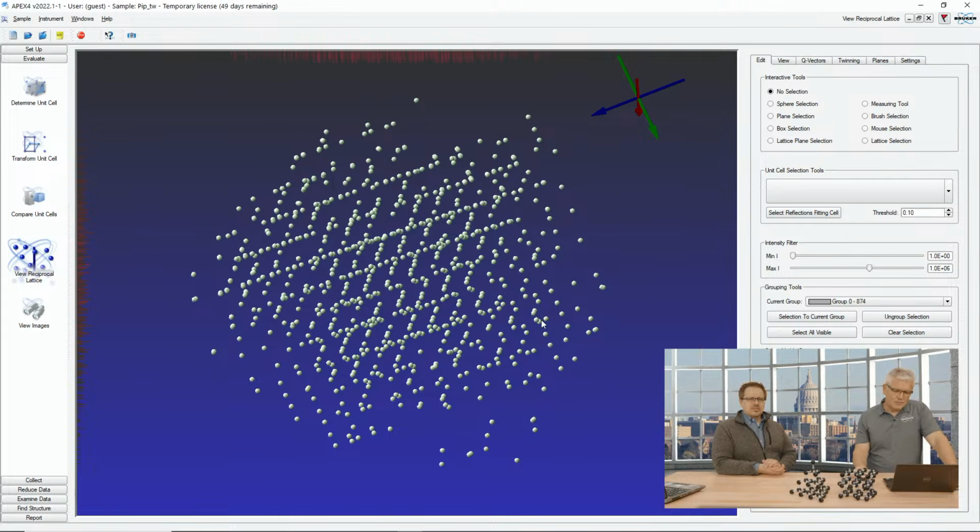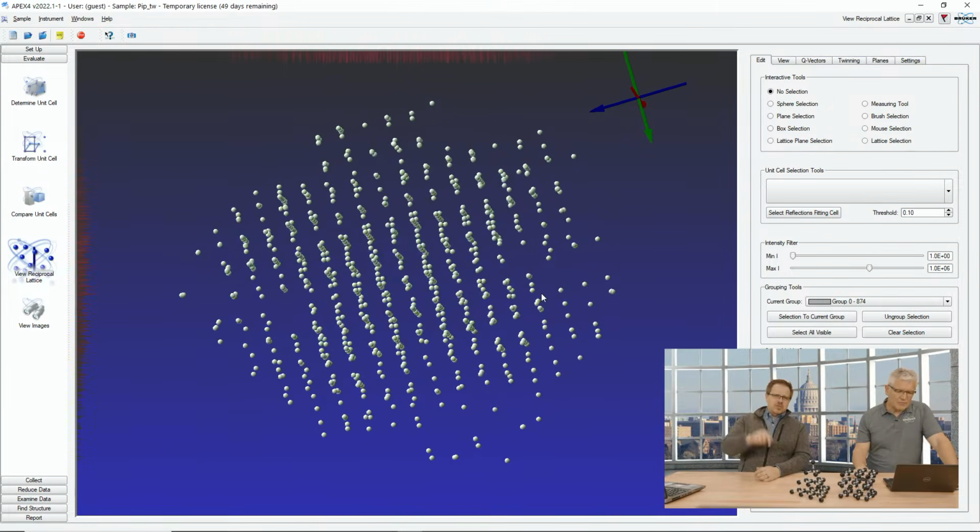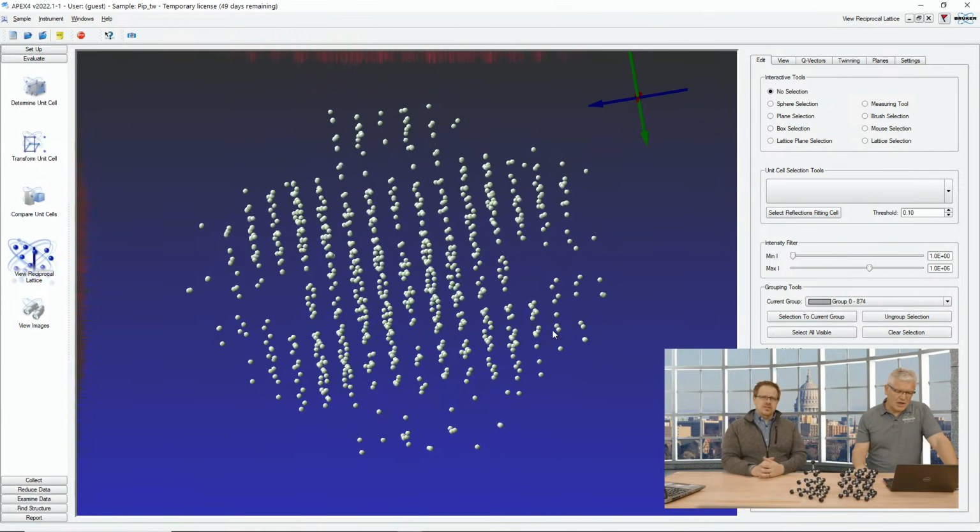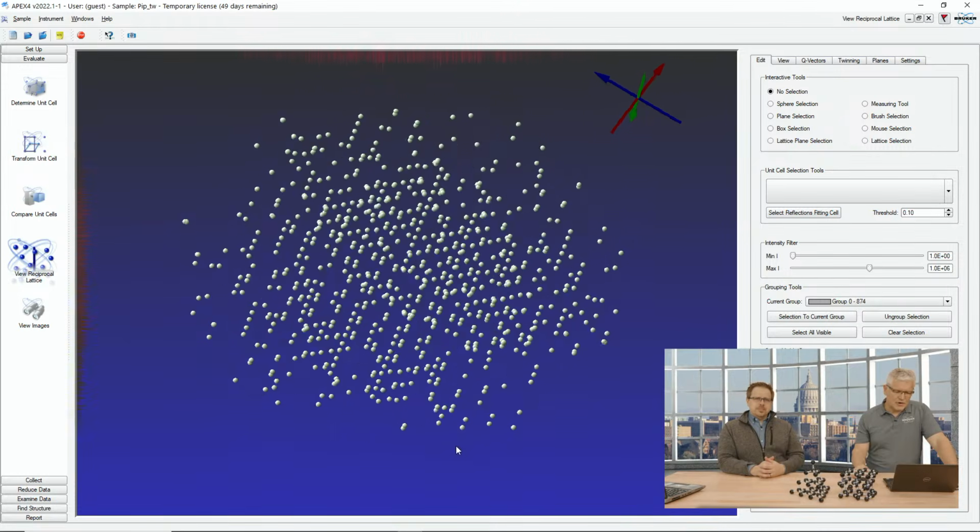right here, we already see that something is not quite right. In a single crystal, you would expect a pattern that shows rows of reflections and lattice planes. Right here, the zigzag is a really good sign for twinning, and you get an idea that you have two lattices in reciprocal space that penetrate each other. Do you see the zigzag? Yes, it's like a little lightning bolt. Typically you would only get nice lines.